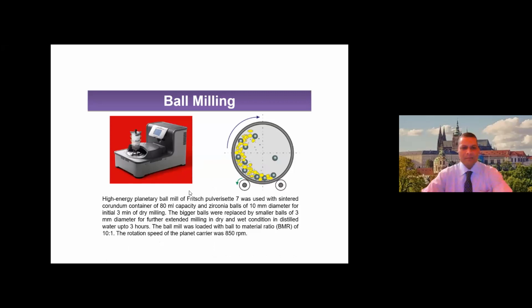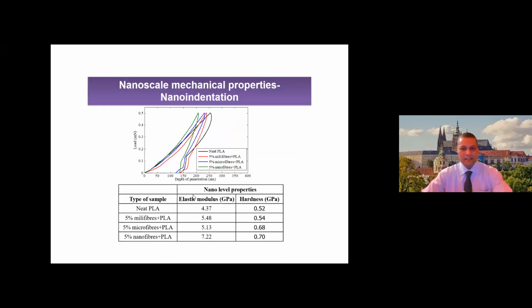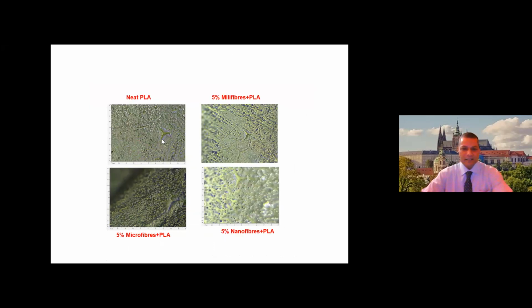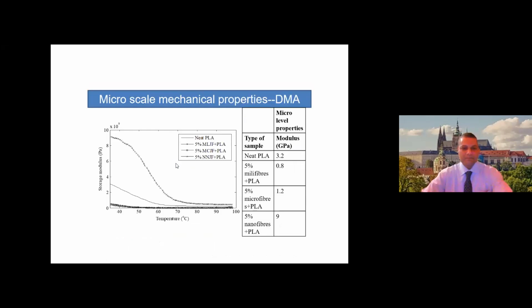So this is the device by which mechanically the nanoparticles can be created from macro materials, and I already explained about indentation. Indentation is commonly used in the metallic industry. For polymers, a very minute nanostructured indenter penetrates into the material surface, and the time required for recovery of this indentation mark shows how elastic the interfacial bond is between the particle and the matrix.